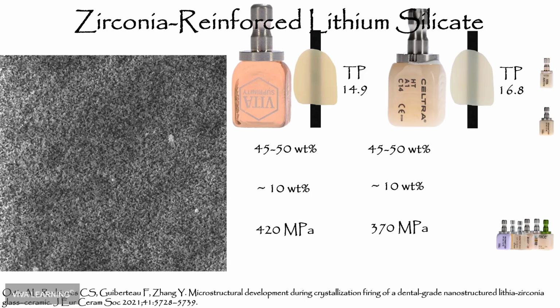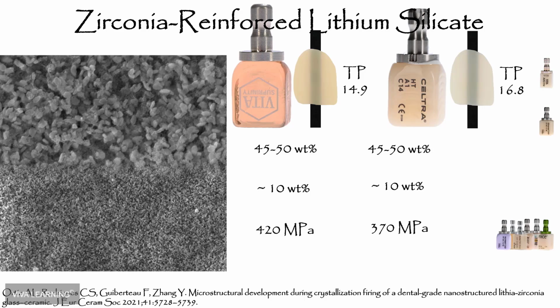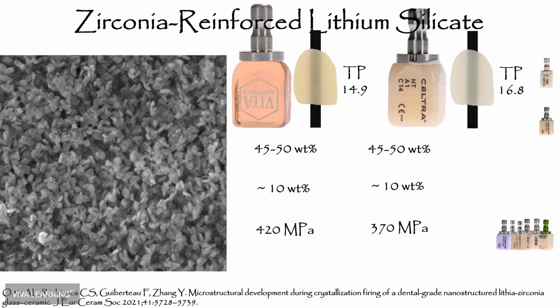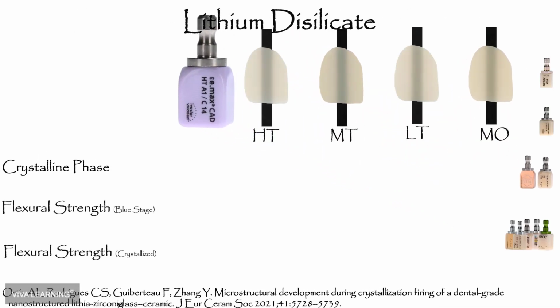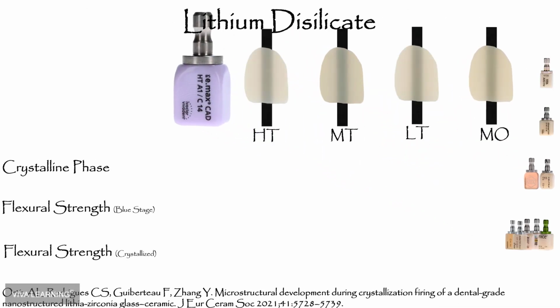When we look at them under SEM, we can see that lithium silicates are relatively smaller filler particles and more round when compared to lithium disilicate that are more elongated fillers. And we see that these crystalline structures do not prevent the crack propagation as well as lithium disilicates. And that takes us to the last category of glass matrix ceramics, which is widely used, lithium disilicates.